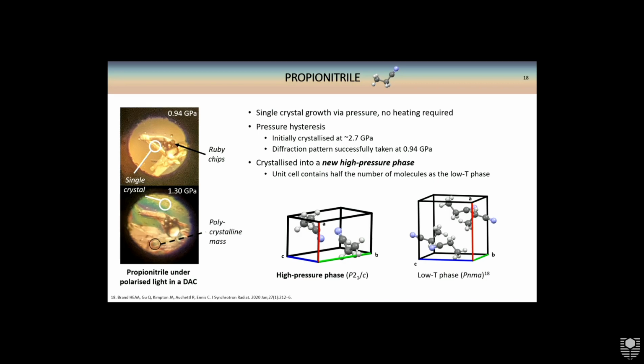Excitingly, we found that the propionitrile actually crystallizes into a new structure at high pressure, different to the low temperature structure I have over here. The unit cell has half the number of molecules as the low temperature phase, and the intermolecular interaction between the nitrile group on one molecule and the hydrogen from a methyl group on another changes as well. The angle of the interaction becomes a lot closer to 180 degrees. And this was at increasing the pressure to 1.3 GPa.